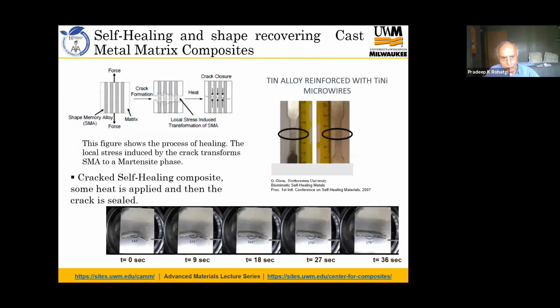We have extended the technology of metal composites to produce self-healing materials where, if there is a crack, it can heal itself. This is done by incorporating fibers of the shape memory alloy nitinol, which shrinks and remembers its shape, in the matrix of aluminum. When you stretch it, the aluminum fractures and you see a crack. If you heat it, the nitinol fiber, which is still intact, shrinks and closes the crack. So in this metal composite, you can get self-healing of a crack. In this tensile bar there is a crack, and after heating, the crack has disappeared. So this is an example of a self-healing metal matrix composite.